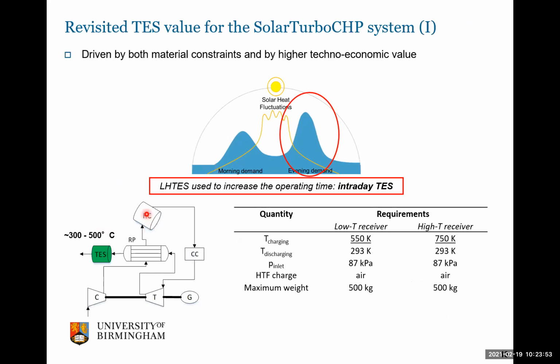So instead of being fully integrated in the solar receiver, here, with a slightly different schematic, the economic case for this application led us to reconsider a slightly lower temperature thermal storage that is recovering essentially the heat wasted at the outlet of the recuperator, at around 300-500 degrees C, and this heat can then later essentially be delivered to the end user during nighttime.